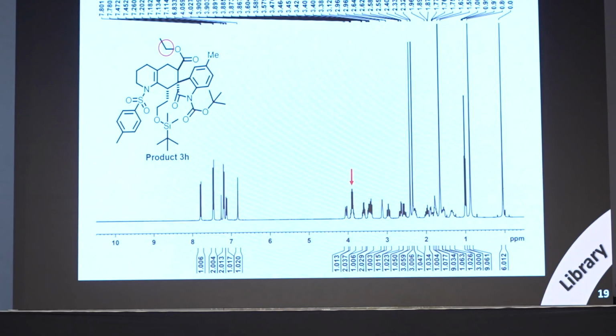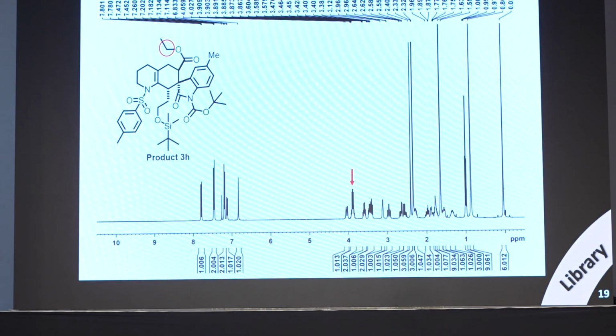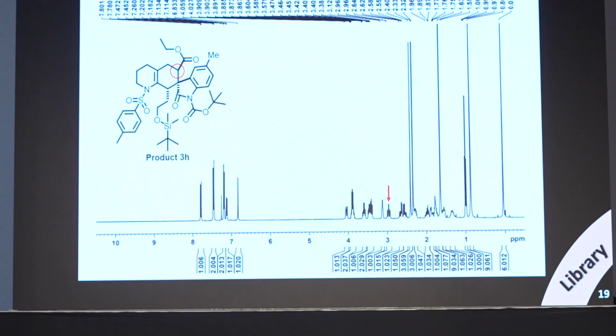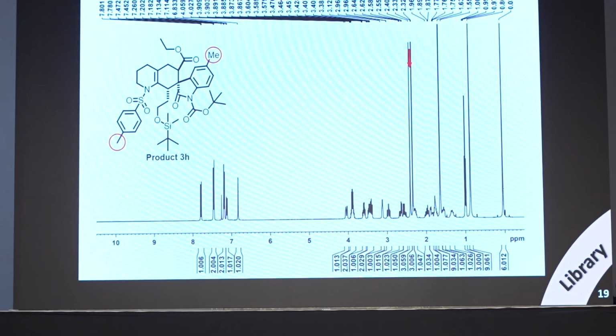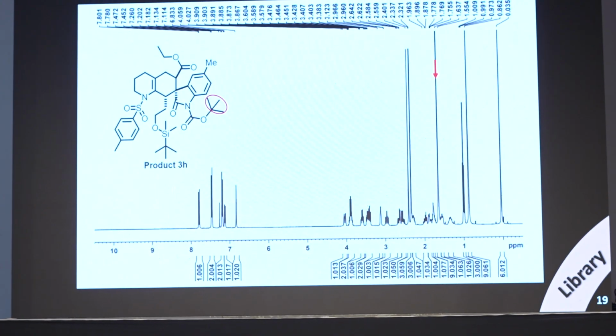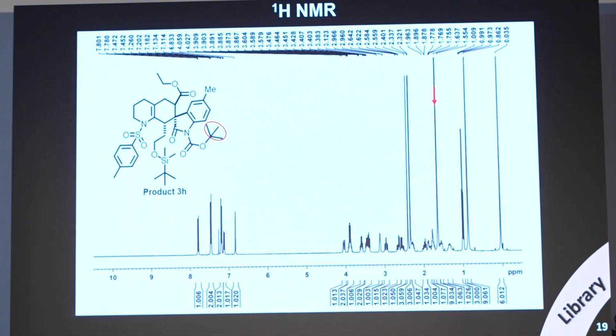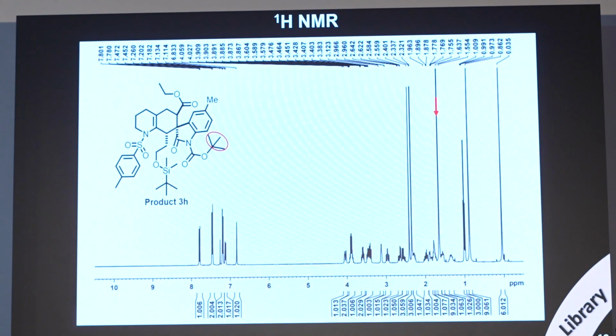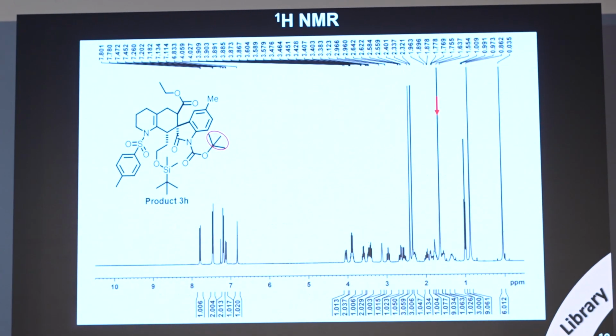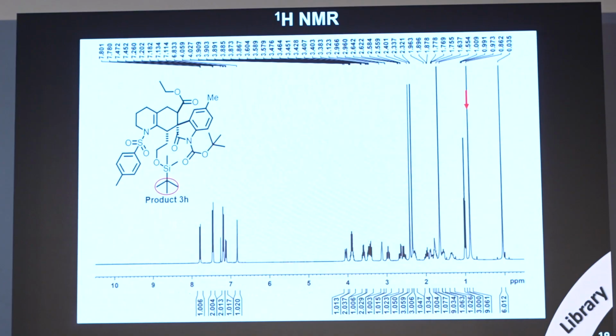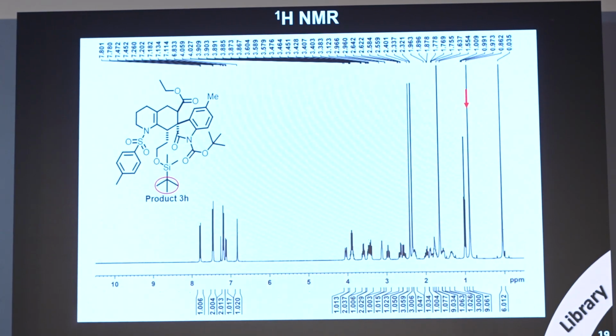Here, that oxygen attached CH2 resonates at 3.8. I mark some important peaks for understanding the molecule structure. Then this proton resonates at 2.9, and the next, this 2-methyl, resonates at 2.5. And here we are having 2 tertiary butyl groups. One is oxygen attached that resonates at 1.6, and another one that resonates at 0.9.